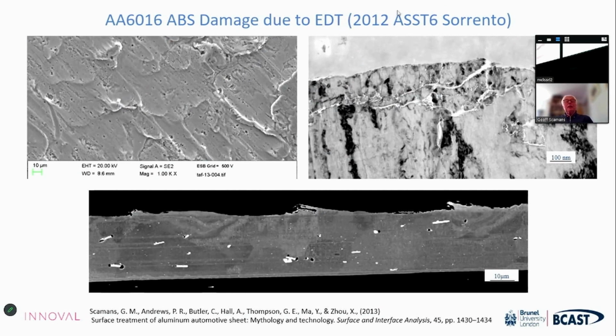And it turned out that understanding deformed surface layers on aluminium can body sheet was absolutely vital in protecting some of the markets for can body sheet across the world. Because if you don't control the deformed surface layer and you don't get it cleaned away properly, you end up with problems called yellow can and galling. And this was almost catastrophic for Novelis in preserving their can body sheet market in Asia until they had this work done at UMIST, and were able to understand it was all to do with deformed surface layers, and they had to make sure that they were either minimised in production or properly cleaned off before the can sheet was sold.